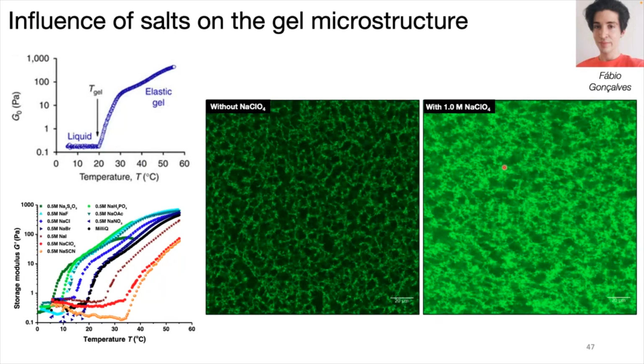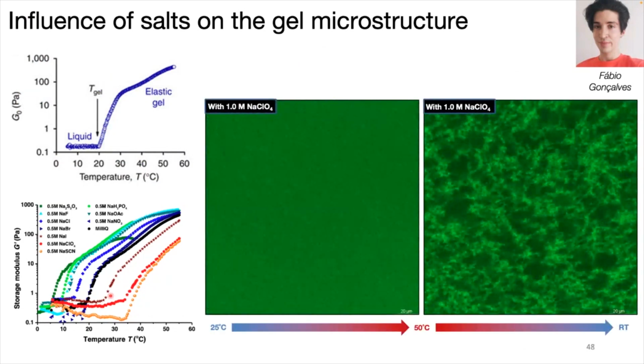And one thing that we really wanted to do was to follow the gelation process, but we could not do it if it's at 18 degrees, because then you have to cool down from room temperature, and we didn't have that possibility. But if we add the salts, we can actually warm up, because we moved the gelation temperature to a higher temperature, and then we could follow it.